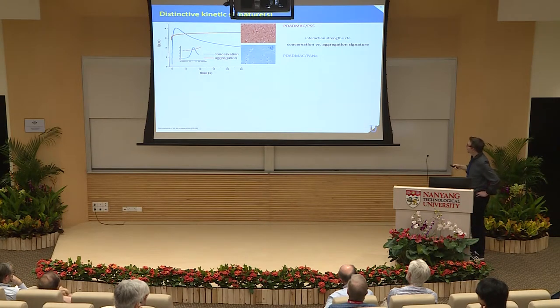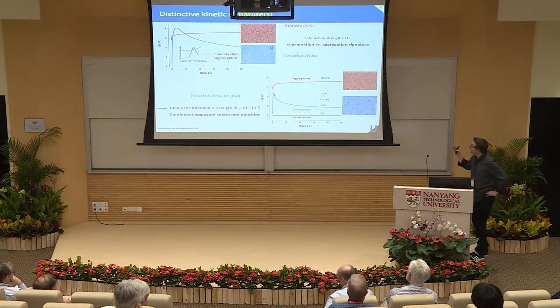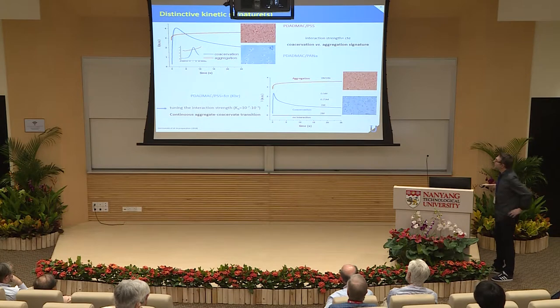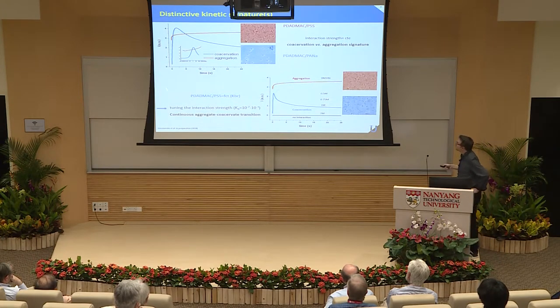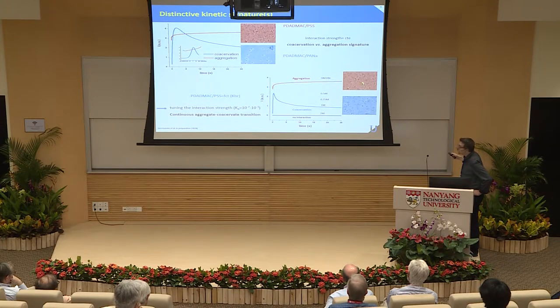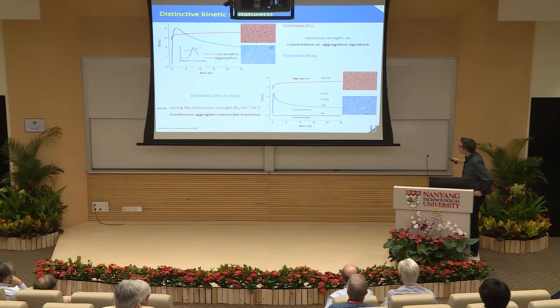Coacervation is a super-fast transition that starts around a couple of milliseconds after mixing the solution. Aggregation lasts much longer. Now, if we keep the same system — PDADMAC-PSS, which gives rise to aggregation without salt — and we tune the interaction by adding salt, it's possible to go through different phases. We start with aggregation, and by increasing the salt content, we are able to go to the coacervate phase region, with a neat signature from stop-flow experiments.